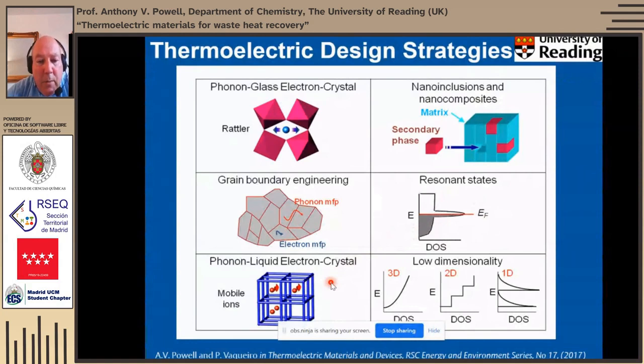And this is a material where we have some sort of underlying lattice, with mobile cations usually within that lattice. And at some critical temperature, those cations, effectively that sublattice, either melts or partially melts, and that then could lead to significant reductions in thermal conductivity.